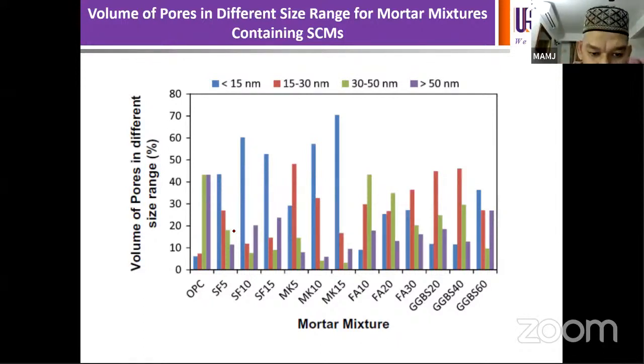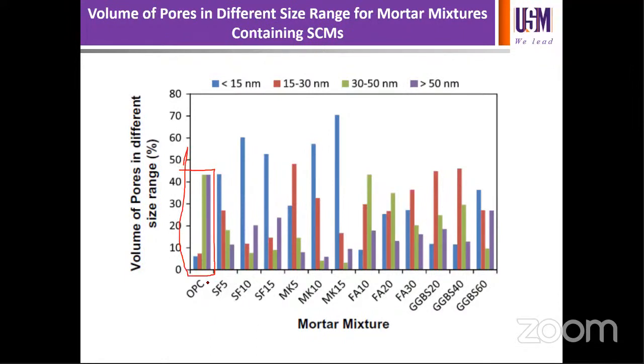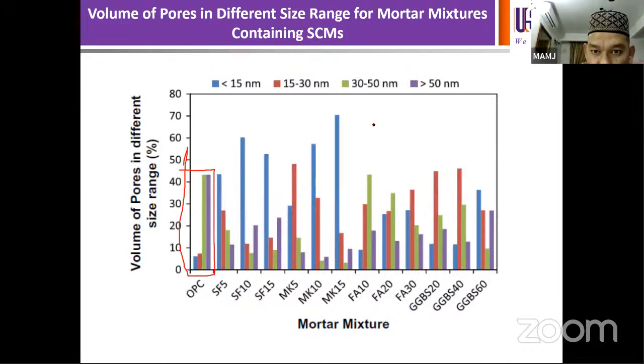All right, so this is a figure showing the pore size distribution in the different mortar mixtures. We can see significant differences in terms of the trend. Based on this, the ordinary Portland cement or the control mortar is on the most left. So it has a significantly greater amount of macropores in the range of 30 to 50 nanometer, as well as greater than 50 nanometer. While those containing silica fume and the other mineral admixtures in general have a significant amount of smaller pores, less than 15 nanometer, and there are some in the 30 to 50 nanometer.